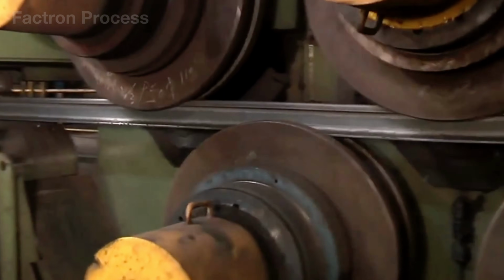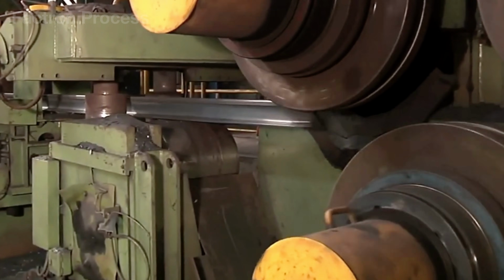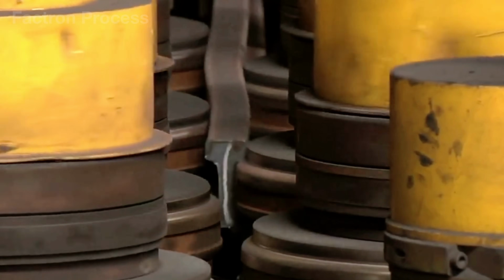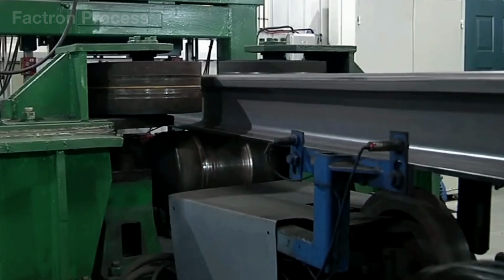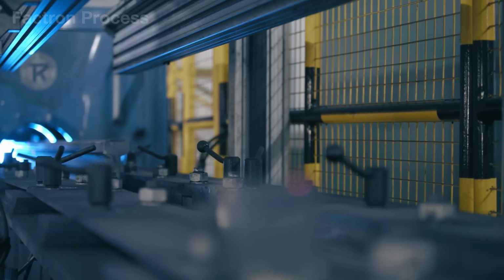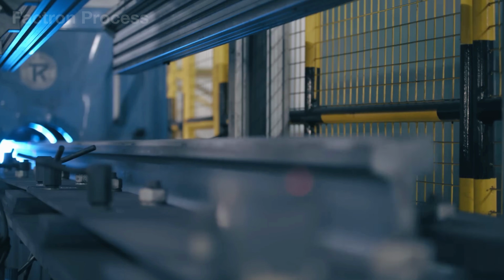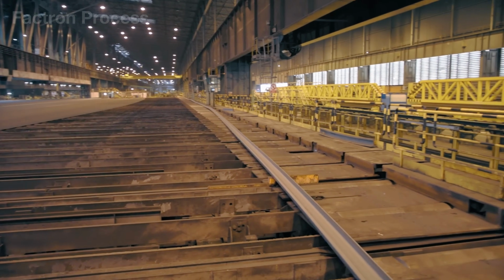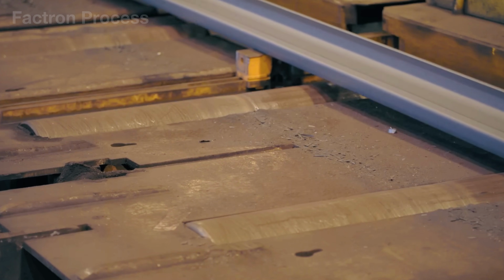If the force is too low, the rail will spring back into a curved shape. If it is too high, residual stresses can rise sharply, creating a safety risk during train operation. This near-perfect straightness removes minor surface irregularities, helping prevent vibration and noise as high-speed trains pass over the track.